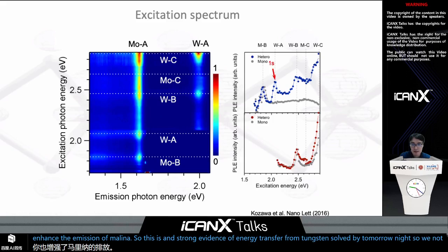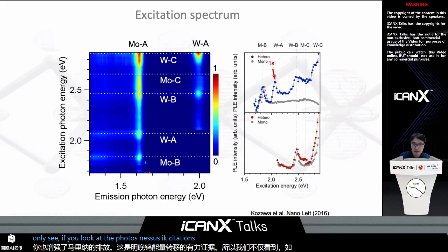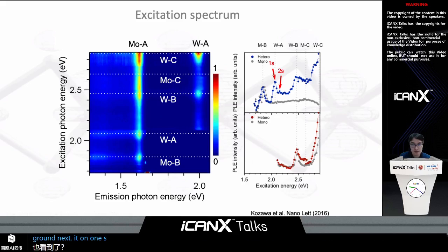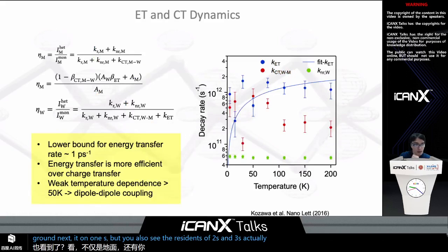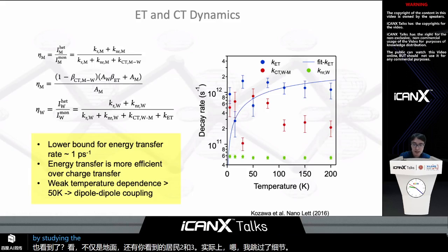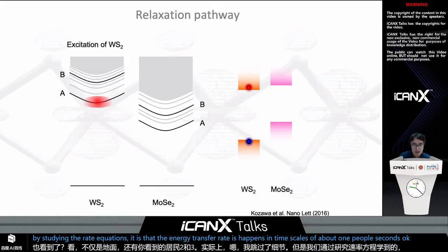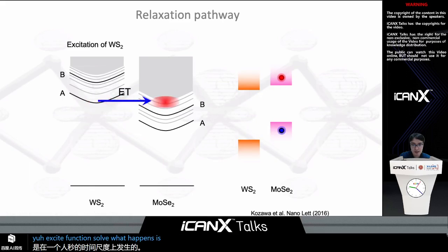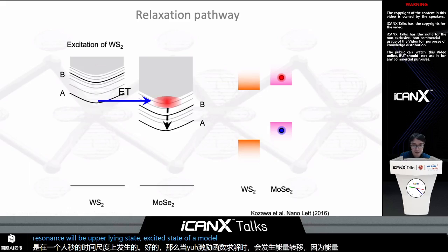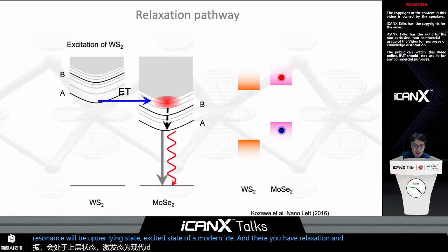If you look at the photoluminescence excitation spectrum, you see not only the resonance of the ground exciton 1s of tungsten sulfide, but also the resonances of the 2s and 3s excitons. I will skip the details here, but what we learned by studying the rate equations is that the energy transfer happens on timescales of about 1 picosecond. When you excite tungsten sulfide, energy transfer occurs because the exciton energy of tungsten sulfide is in resonance with an upper-lying excitonic state of molybdenum selenide. And there you have relaxation and emission of light.